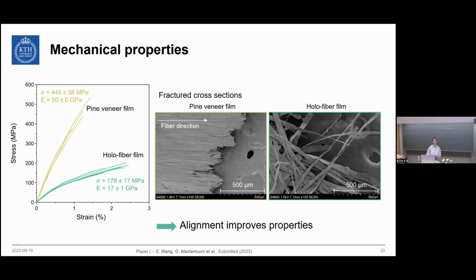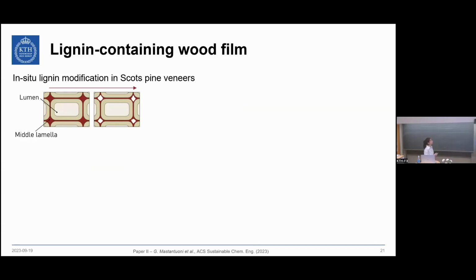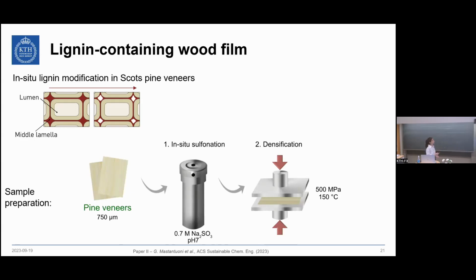However, we did need to delignify the material. So then we wondered, can we actually keep the lignin inside? In this case, what we wanted to do was modify the lignin, only partially delignify the material, so that the cohesion between the fibers could be better preserved. We used sulfonation, so we simplified the process to only one step, followed again by densification. Here we needed to go at a slightly higher temperature, because we wanted to go above the glass transition temperature of lignin, which in this case was around 127 degrees.